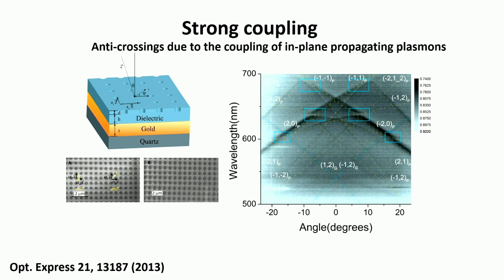For example, if the modes are non-interacting, they just cross over in the dispersion plot. Here, these are non-interacting plasmon modes. However, you also see modes which are boxed here, regions where the modes are actually anti-crossing. These are examples of the strong coupling regime, where these in-plane propagating plasmons interact with each other because of the energy and momentum conservation happening in these structures.